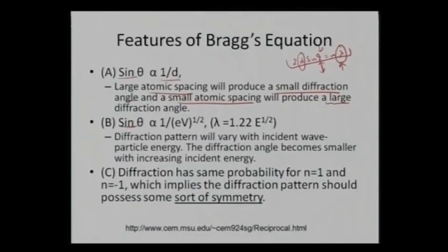So for higher energy, I can see diffraction at much closer points, where theta is very low. The diffraction pattern will vary with the incident wave particle energy, and the diffraction angles become smaller once I increase my incident energy, or once I reduce my lambda. My theta decreases as I decrease my lambda. So that is a direct dependence of theta on energy or wavelength.